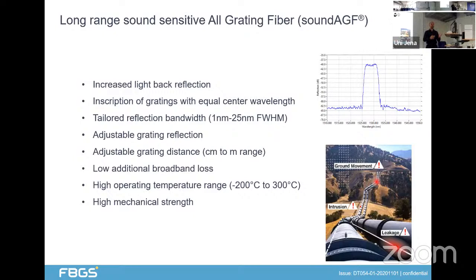That also means that for writing these grating sensor dots in the fiber, the distances can range from centimeters up to meters, depending on the application. What is also required is that the gratings have no high loss. If I have several hundreds or thousands of gratings, each grating needs to have a low loss, and that is possible with both technologies we have. And the good thing is that these enhanced backscatter fibers can also work in a quite broad temperature range, from -200 degrees up to 300 degrees Celsius. And as we use these two technologies, we have a high mechanical stability.